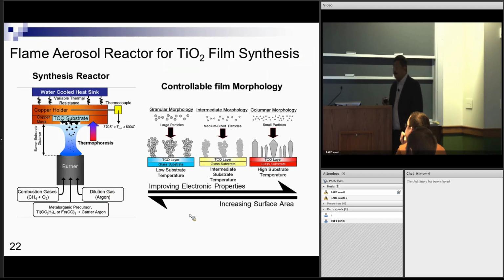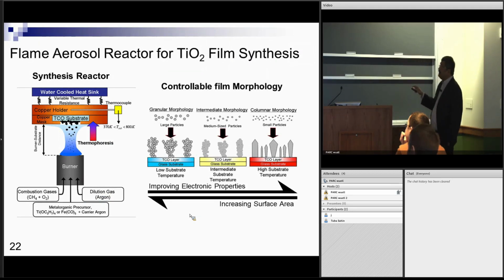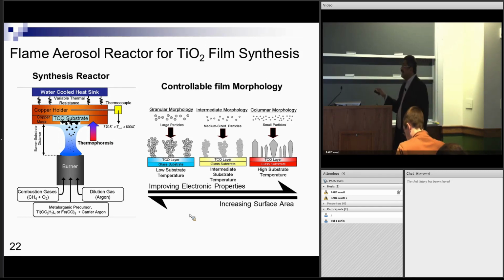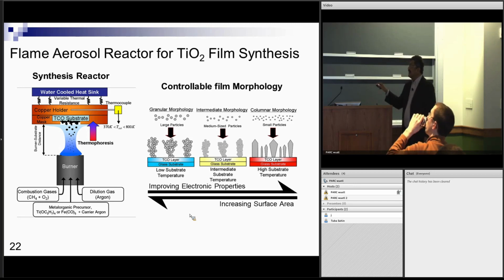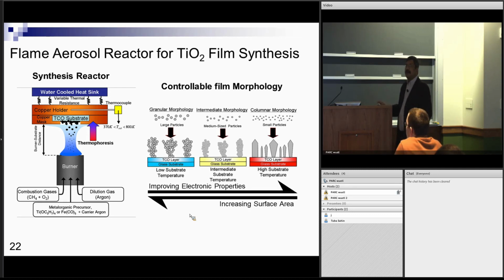So I'm going to show you some systems where I use it to make those one-dimensional structures, right? I take a flame, I bring in a precursor, and these are all metal organic precursors, and depending on what I control out here, I can get different morphologies. We call these morphologies. So this is an extremely high surface area structure, and if I'm promoting localized chemistry, as I told you, this may be good enough. But if I want to pull the electrons all the way to the substrate, this is not good, because there is a grain boundary resistance, right?